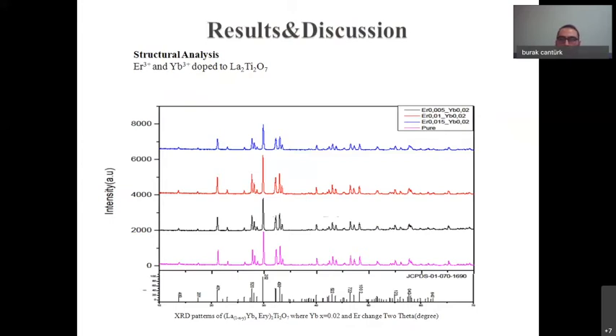without signs of impurities, and there is an absolute correspondence with the reference cards, and no extra peaks were noticed. This points out that the ytterbium and the erbium doping does not result in any second phase formation and fully dissolves in the lattice as a substitutional solid solution.